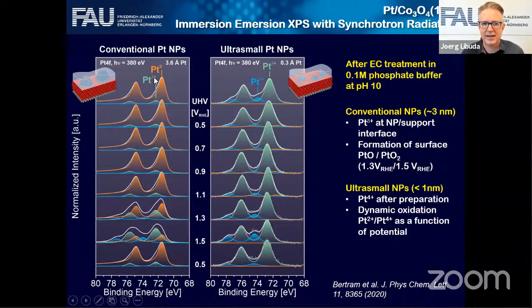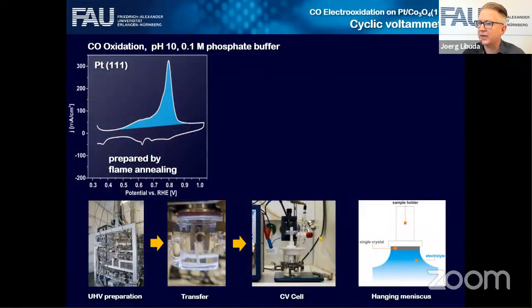Also, we see this platinum delta plus and platinum zero species in larger particles and at potential 1.3 volts versus the reversible hydrogen electrode, we really see oxidation, surface oxidation of these platinum particles. That's expected. And for the small particles, the electronic structure, as I explained, is different. We see this partially oxidized platinum species only, along with some platinum 4 plus species in the system. So now let's look at the chemistry on these surfaces.